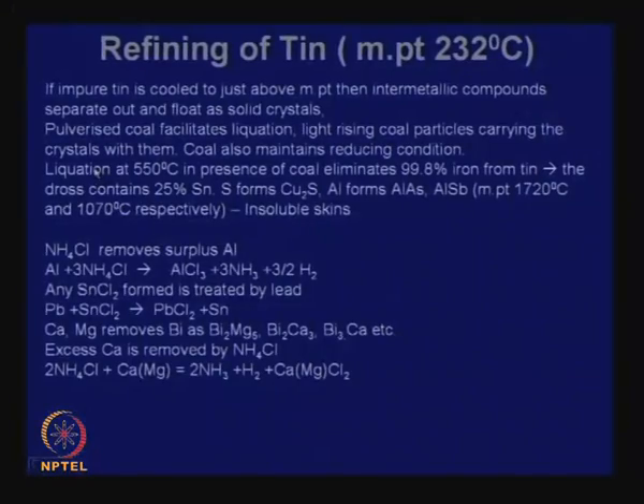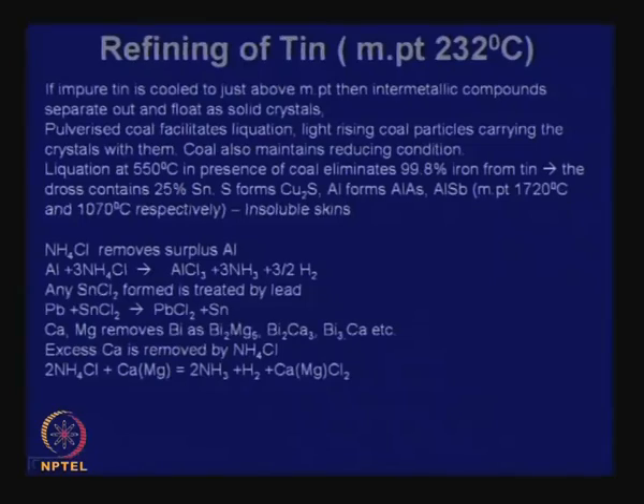Now, if you go, as I mentioned a bit earlier, to a slightly higher temperature of 550 degrees, in the presence of coal, 99.8% of iron from tin will get separated by liquation, thanks to the phase diagram. There is a complete separation of pure tin and iron containing small amounts of tin. That is how the phase diagram tells us. The dross contains 25% tin. Of course, it depends on the temperature at which you are operating. If you are doing liquation at 550, you will get pure tin and you will get an iron-tin alloy containing 25% tin.